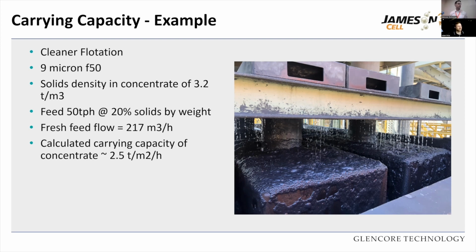From this, using our carrying capacity model, we can equate that our maximum theoretical carrying capacity will be roughly 2.5 tonnes per metre squared per hour.